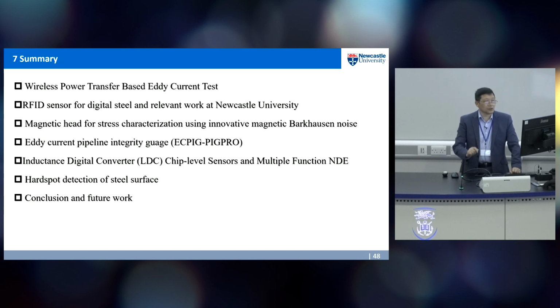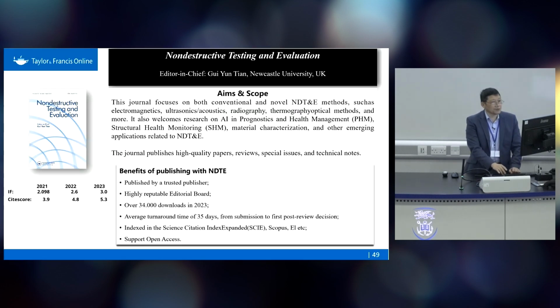So quickly, I just show you what we use different eddy current probes for different applications, not only sensing themselves, but also including communication, using wireless or power transfer communication. We also apply different kinds of magnetic principles, for example magnetic Barkhausen noise, using domain wall tuning, and we also extend to multiple function sensors, including thermography and resonance sensors for different kinds of measurement: defect, microstructure, and stress measurement.